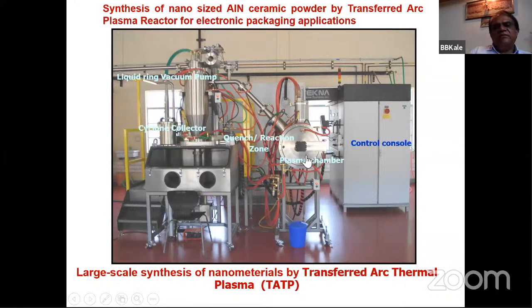This is a plasma reactor. In this plasma reactor, one of the cathodes is metal. Suppose I want to make aluminum nanoparticles, the aluminum can be put as one cathode, and the temperature goes to 3,000 to 4,000 degrees centigrade. Aluminum gets evaporated, and at the atomic level it gets quenched, and we get nanopowders of 20 nanometer, 30 nanometer, 100 nanometer. The advantage is that scaling up of the nanoparticles is very easy. We get 100 grams per hour capacity of any kind of metal nanoparticle, metal oxide, metal nitride. So these are very unique machines.